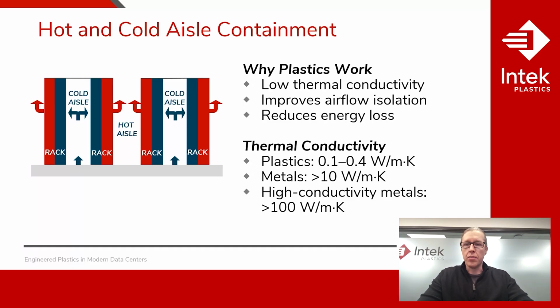So using ASTM D5930, we measure how heat moves through that material, often in plane and through plane, but plastics typically fall between 0.1 and 0.4 watts per meter Kelvin. Common metals, just for reference, exceed 10 watts per meter Kelvin, and high-conductivity metals like aluminum or copper exceed 100 watts per meter Kelvin. So this massive difference makes plastics ideal for containment panels, louvers, ducts, and other structures that maintain strong separation between hot and cold aisles.